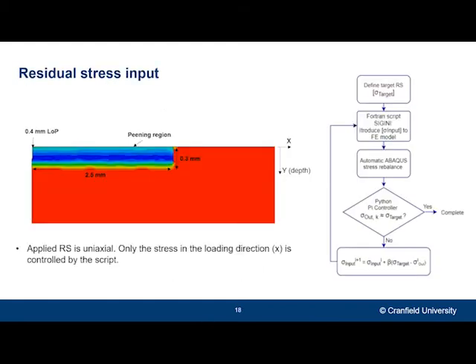So a crucial step for these FE model developments was to create an iterative algorithm to introduce the desired residual stress fields into the FE model. This was needed because when you try to apply a predefined residual stress field into an Abaqus model using a subroutine called SIGINI, Abaqus tries to rebalance the stress fields because the FE code is trying to find the equilibrium condition. So this will result in stresses in the end that are different from the target stress that I was trying to apply.